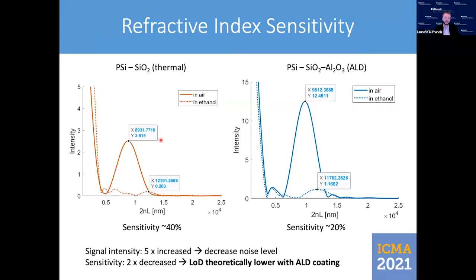But what about the sensitivity? In that case, we can see that the sensitivity is lower, in fact, which is still to be understood in detail. We have a signal intensity which is higher by about 5 to 6 times, which will also decrease the noise level. But the sensitivity is about twice lower in this case. So finally, the limit of detection should theoretically be lower with the ALD coating on the porous silicon material.